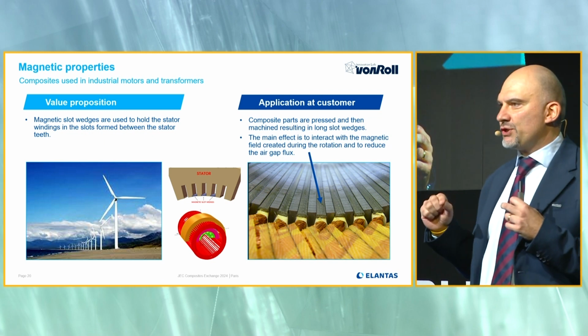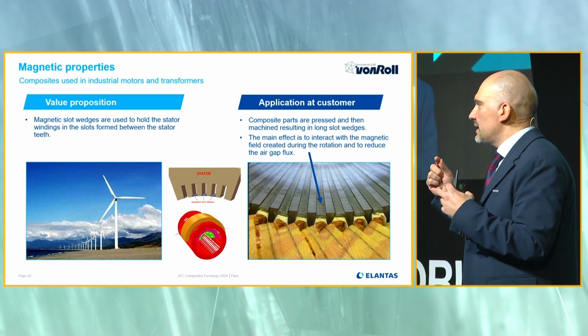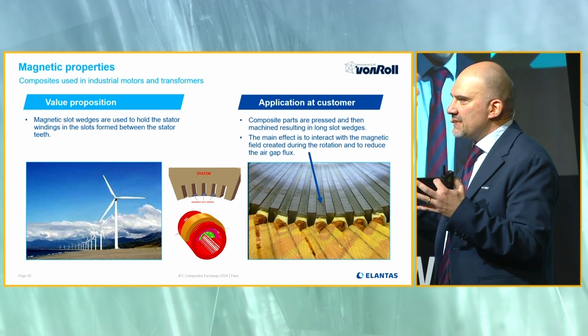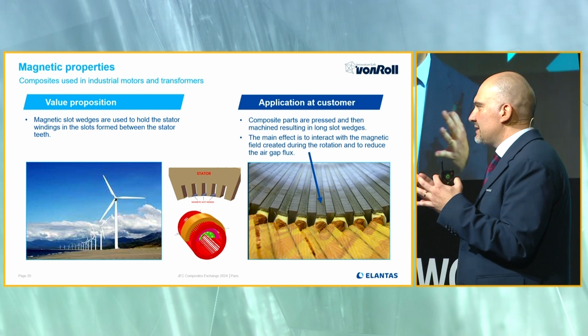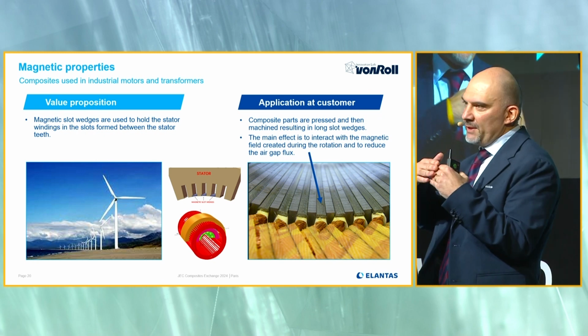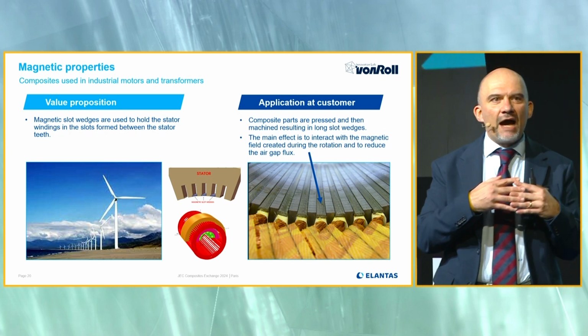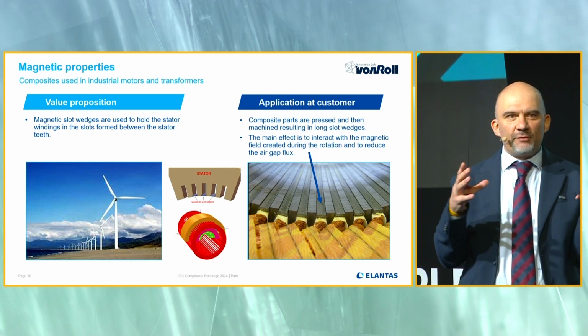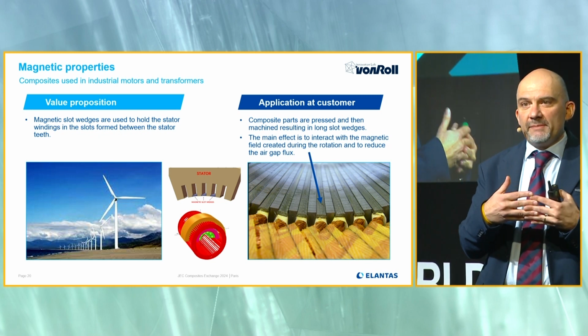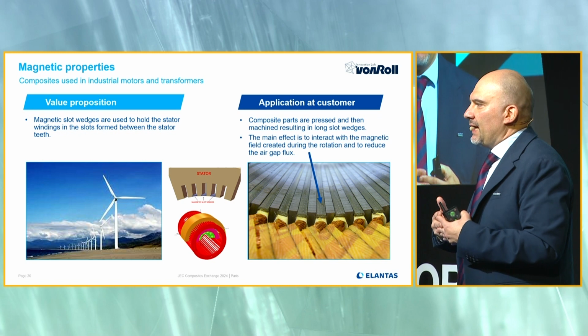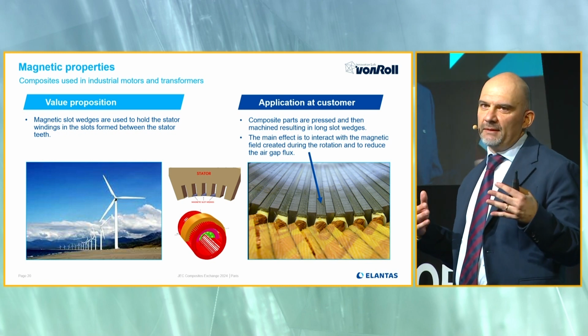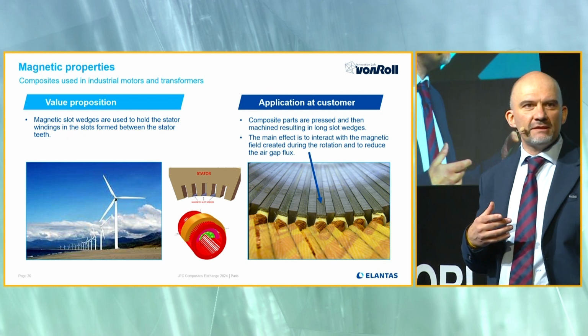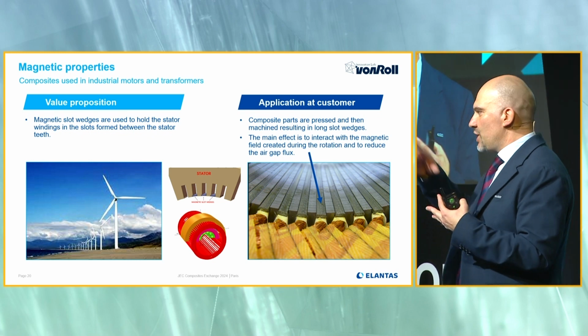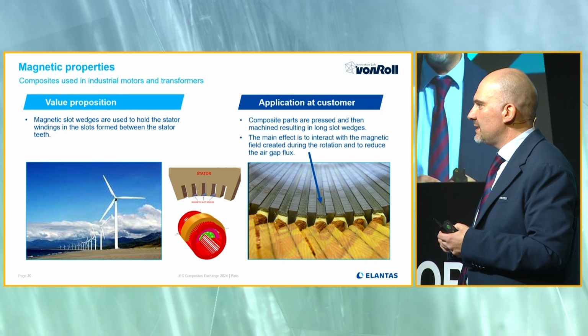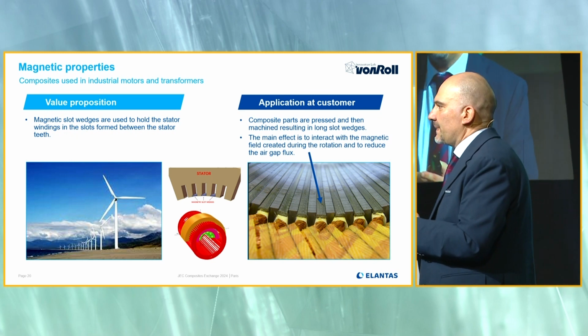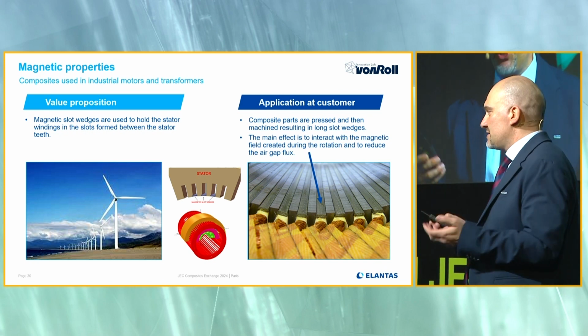The main issue in this industry is that in order to keep continuously the rotation of the rotor, this creates an electromagnetic field, and this electromagnetic field is creating some air flux in the gap between the rotor and the stator. So the challenge is how we can counter-react or balance this electromagnetic field so that it does not create any problems in the acceleration of the rotor. What we discovered is that we can play on the magnetic characteristics of this composite part, and by playing with the magnetic part, we can change the electromagnetic field which is around this part. And this is improving a lot the speed of the machine, so basically the efficiency of the motor.